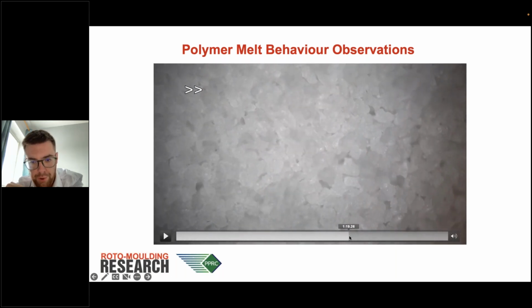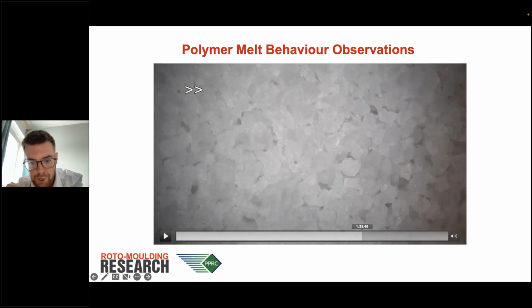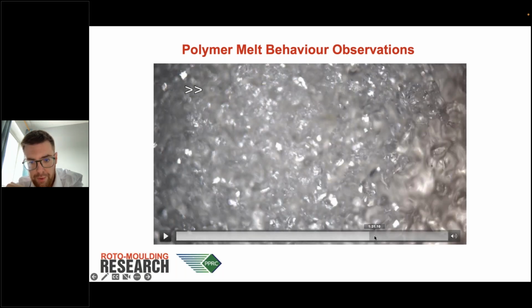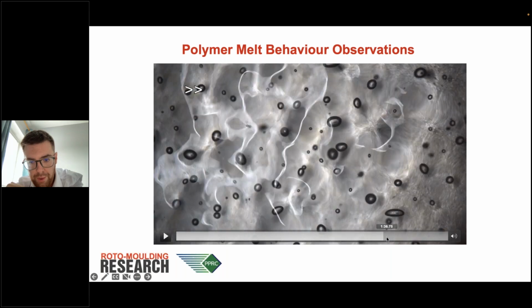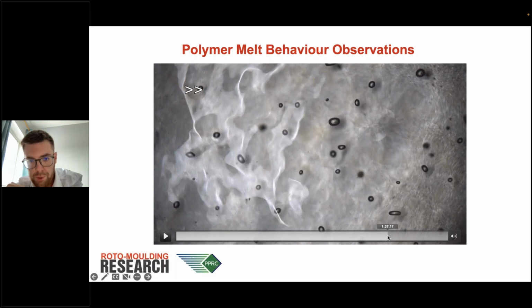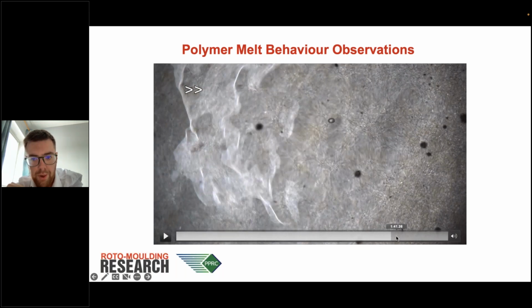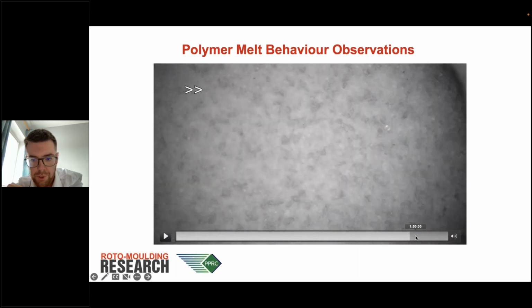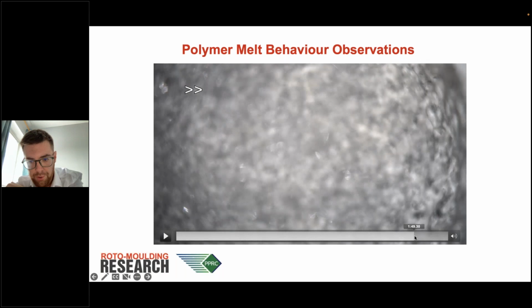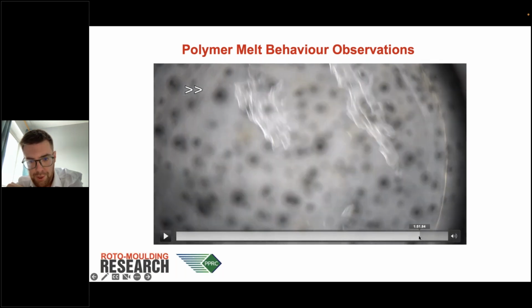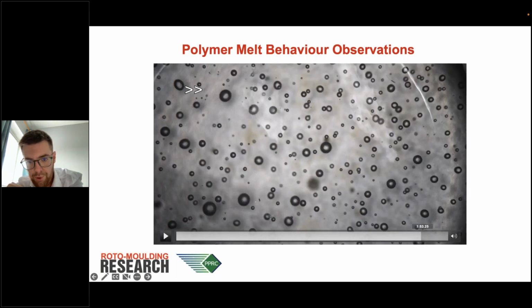If you then do the same thing under a vacuum from the start, and then remove the vacuum, so from this point to that point, the vacuum has been removed, you can see there is a dramatic size reduction in those bubbles, and eventually then you end up with no bubbles. So that's a pretty easy way of removing the bubbles from these polymer melts. The next thing then that you can do, interestingly from a foam point of view, is you can pull a vacuum after the bubbles have been formed, and you can get them to grow in size like that.